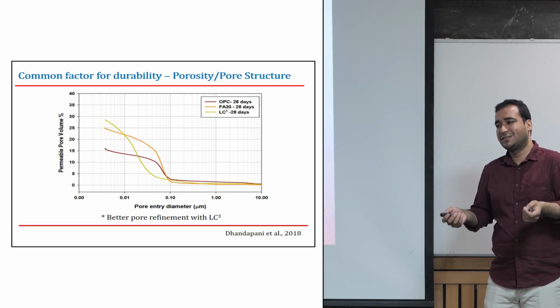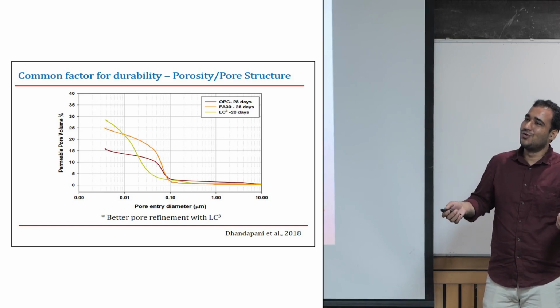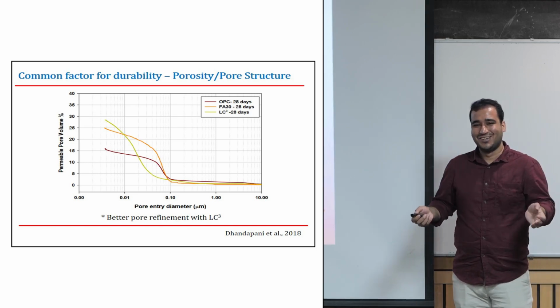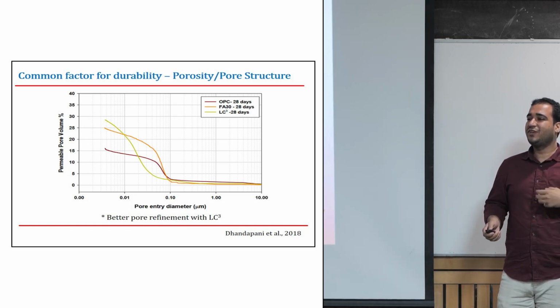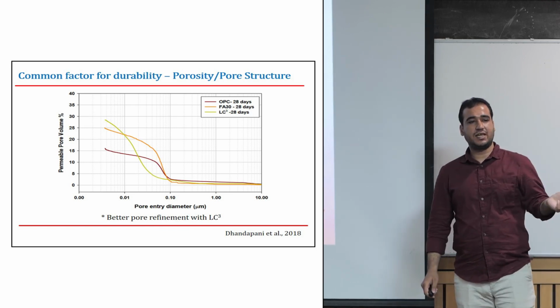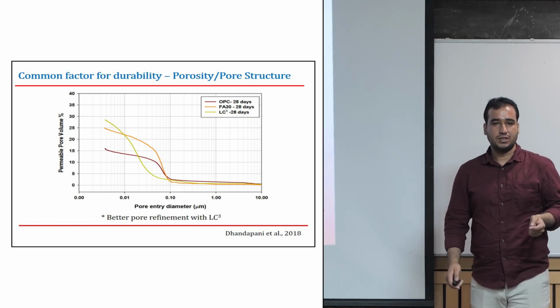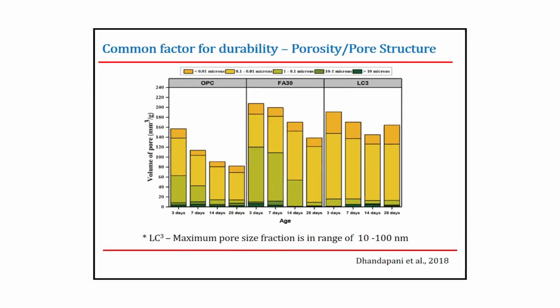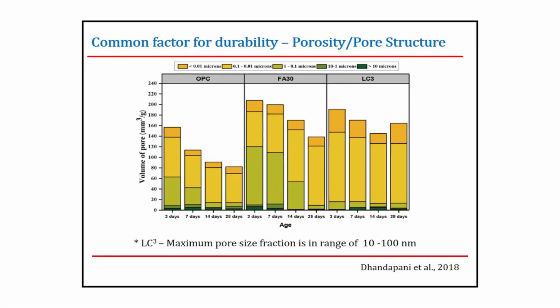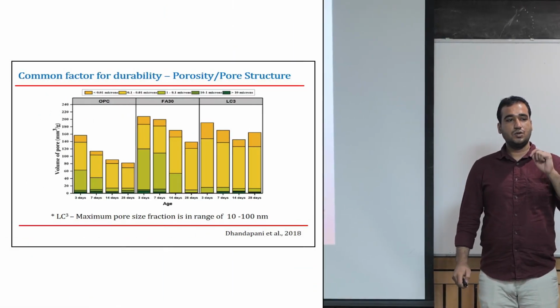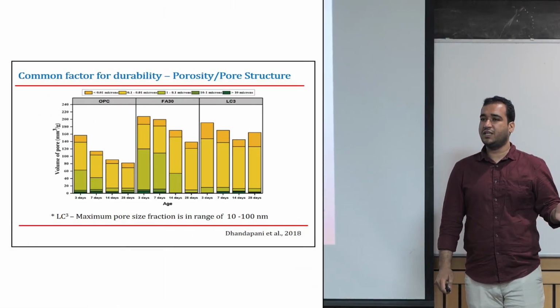Most of us think yes. To be honest, I was the one who was thinking that. So, not a big thing. It happens. We feel that it's the porosity that decides, but it's not actually the porosity. It's more the pore size distribution, the interconnectedness of these pores, the surface charges of pores, the fractal dimensions. There are lots of other things. Now, the interesting thing here is, in the case of blended systems, say PPC or LC3, compared to OPC, your pore size distribution is way different than OPC.